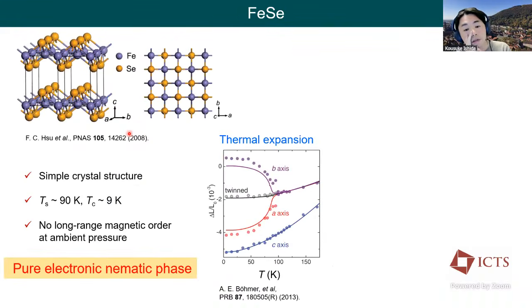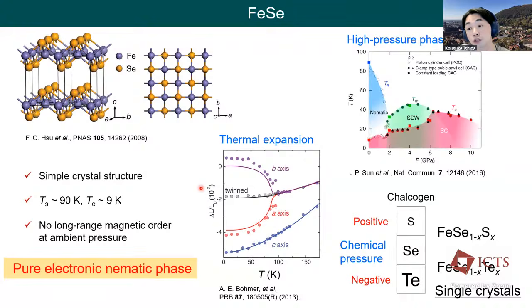To address this point, iron selenide is a key material. This compound displays an electronic nematic transition at around 90 Kelvin, but there's no long-range magnetic order or any other intertwined orders down to zero temperature. So let me say the iron selenide possesses a pure electronic nematic phase. This pure nematic order can be controlled in several ways. For example, by applying hydrostatic pressure, it can be suppressed very rapidly, but it also stabilizes the long-range SDW at higher pressure.